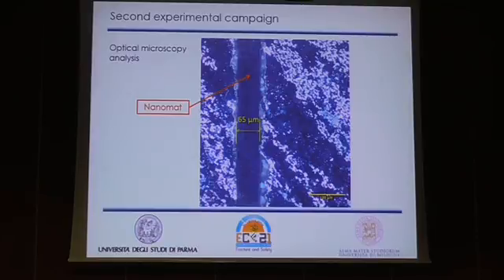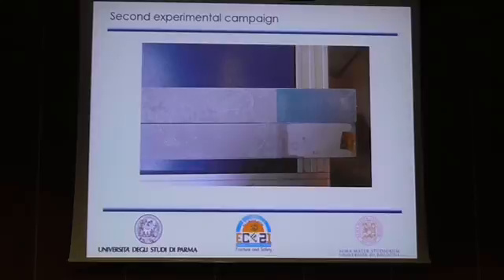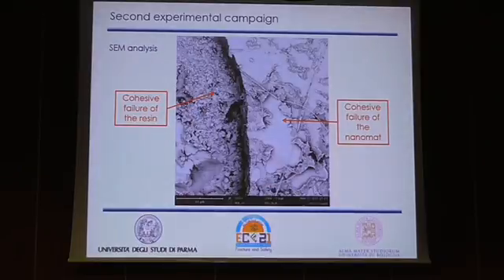Optical microscopic analysis revealed that the nanomat does manage to occupy the whole thickness of the interface, managing to structure the bonding. And a cohesive breakage of the nanomat actually occurs, because it left an extremely thin layer of nanofibers on one adherent and a thicker portion of it on the other. SEM analysis confirmed this hypothesis because even when the surface seems smooth, actually there is a layer of nanofibers covering the metal, to indicate that the crack propagates very near to the interface, to the bond line, but does not actually manage to reach it.